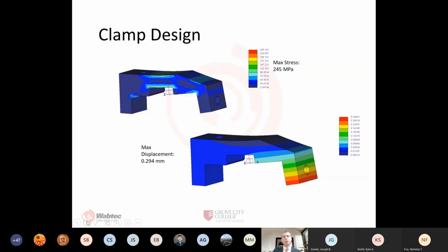Looking at that second figure, the maximum displacement that the clamps will allow between the gear and the collar faces is approximately 0.294 millimeters, which is acceptable to maintain a proper seal with our chosen O-rings. And the final clamps weigh only 6 to 7 pounds apiece, which can be easily lifted and handled.